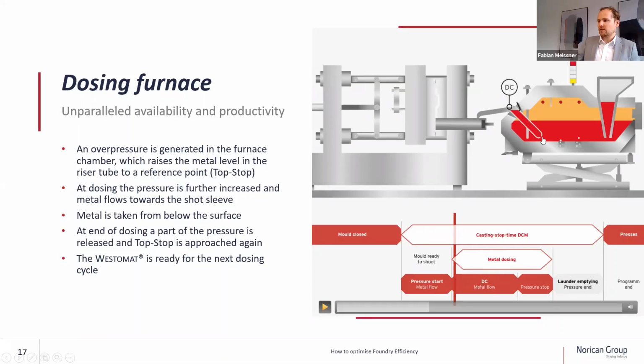You can also see that the metal is taken from below the surface, so we are making sure we're not sucking in any oxides, which are not so many because it's a closed system. But if there are some, then we are not taking them from above the bath surface. Then after we got the signal from the die casting machine, we start dosing into the shot sleeve of the die casting machine.